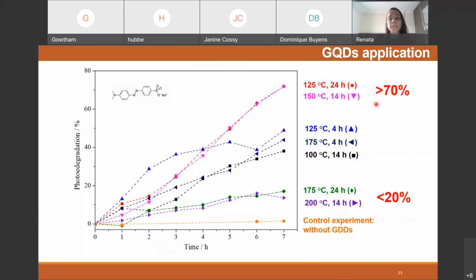And for the suspension obtained at intermediate temperatures, the photodegradation was bigger, 70% of the photodegradation of methyl orange. It is important to say that the control experiment, that is, without graphene quantum dots, showed no degradation of the methyl orange.